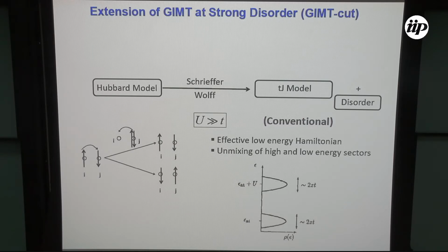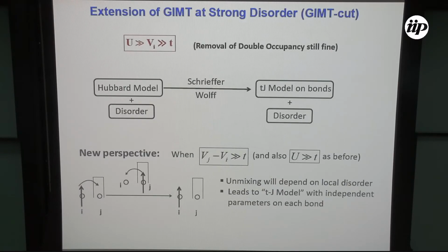Then we added disorder. But is it right if you have strong disorder? No. If we make V much larger than T, but still U is the largest energy scale, so there would still be no double occupancy, but there would be some additional processes. So we have to start with a model which is the Hubbard model plus disorder, then do a Schrieffer-Wolff transformation, and then obtain a model which will have different T's on different bonds. Why? Because you will have these processes. Even if this site is empty, if this site has a high disorder potential, this electron will go there, but since it's high energy, it will not like it. It will come back. It's a virtual process. It will stay at the same place. So there will be virtual processes that you have to take out of the system.